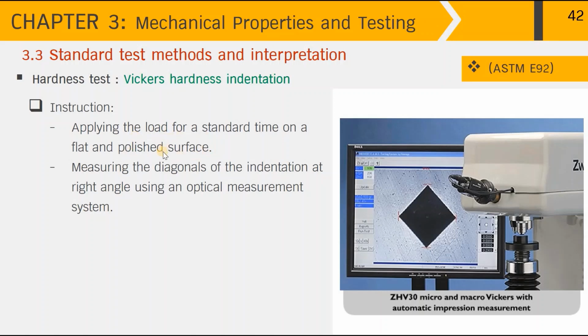This is very important because hardness is very sensitive to scratches. You can't measure the metal surface using Vickers hardness indentation without polishing the metal surface. So it takes time to prepare the sample, and therefore it's not normally used by those involved in metal operations. But this type of test is normally used for research and by those who are involved in advanced materials.